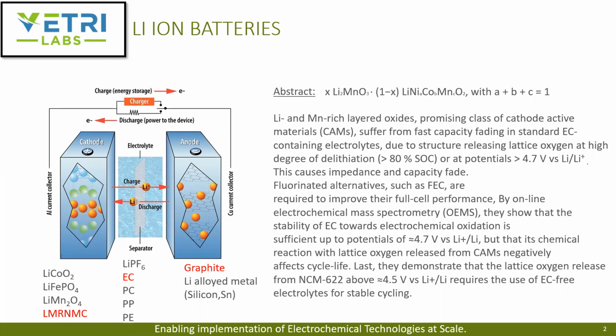This publication is primarily focused on the lithium manganese-rich layered oxides, which are very promising because they have higher capacity, but they suffer from faster fading of capacity, especially in electrolytes that contain ethylene carbonate.